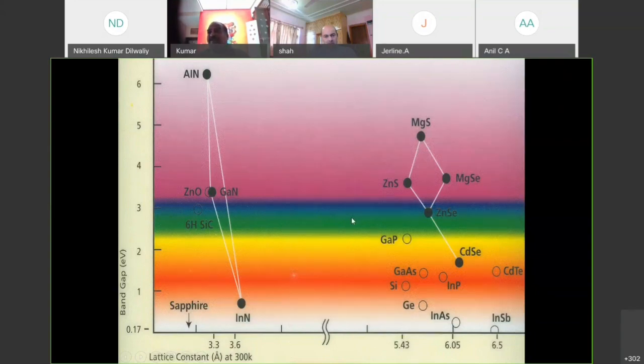So this is a very simple fundamental physics equation which says E equals h nu, and if you do the transformation, the lambda which comes out of this, where E is the energy gap, like 1.1 or 3 eV or 4 eV or 6 eV, will be lambda equal to 1.24 divided by Eg, the band gap. So you can put a definite band gap value, from something like 3.2 to 1.1. You can mix it as you like, make an alloy, and you will get the band gap. From the band gap, you calculate lambda equal to 1.24 divided by Eg, and therefore you get the corresponding light emission.